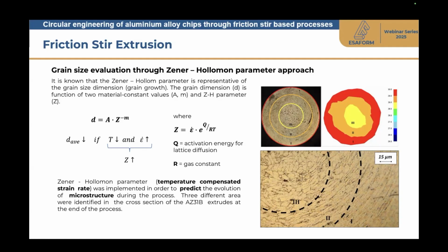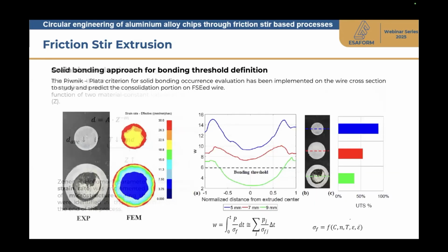And we observed different zones in the wire section, which were, of course, characterized by different values of the Zener-Holloman parameter, and as a consequence, different values of the average grain size during the process. And at the end, the most important thing is that you observe a different grain size all along the section, but of course, with varying extrusion ratio, you have a strong variation in the bonding condition in the wire section. And in particular, as the extrusion ratio is not so high, you will observe